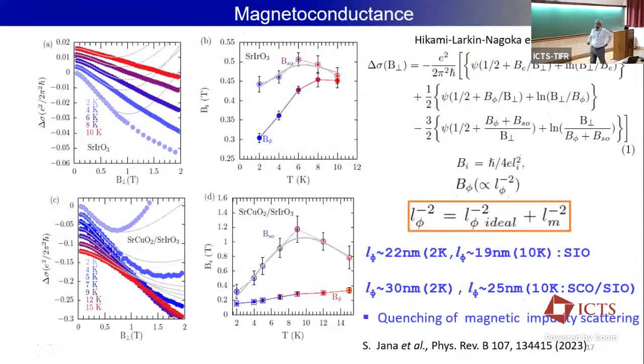Now, to really look at the scattering rates, we looked into the magnetoconductance, and we used the well-developed formalism of weak antilocalization. We calculated the characteristic magnetic fields, B phi and B SO, which are related to the characteristic length scales like this, and we used the HLN equation. I'm talking first about B phi. B phi increases as you increase the temperature, because B phi is related to L phi by this relation.